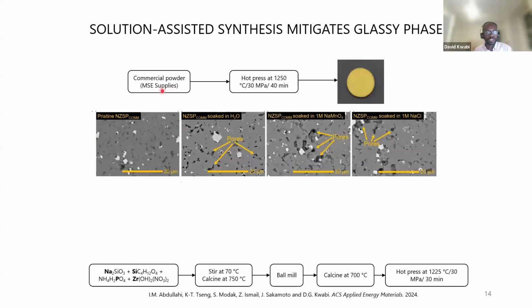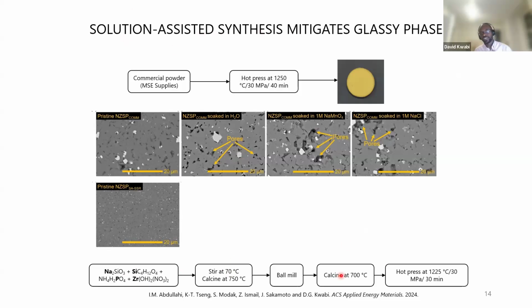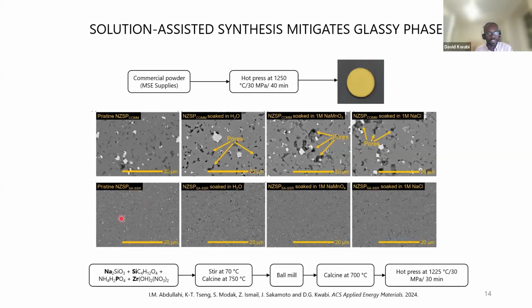So what we then did was to substitute this conventional process for making NaSICON, which results in the glassy phase, with another technique where our precursors are not mixed as solid powders, but dissolved in solution, in what we call a solution-assisted synthesis of NaSICON. So we've modified the process for making NaSICON in an attempt to mitigate the presence of the glassy phase and the secondary zirconium oxide phase. And as you can see on the bottom left here, this new technique was quite successful at doing both. We found that upon immersion in a variety of different electrolytes, we saw very good stability. So we had excellent stability of this new NaSICON formulation owing to this new technique for fabricating it.